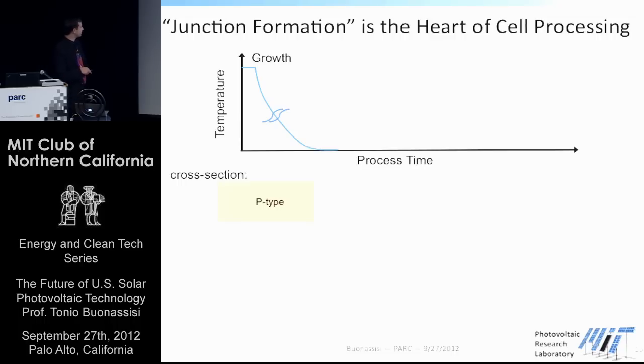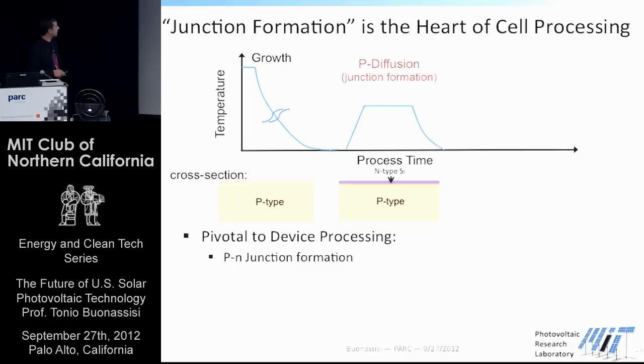This is the cross section of the wafer right here, and it happens to be a P-type wafer. As we continue with our solar cell processing, we first form the junction, the PN junction inside of the device by diffusing in phosphorus. And for the non-initiated here in the group, what this means is we're creating a built-in field that can separate charge. If we just had this bare wafer, light came in and excited an electron hole pair, they would dance around in a random walk. There would be no potential, no voltage, no buildup of charge. Whereas now we have this built-in electrical field, you can separate the charge that's generated by the sunlight. Very critical step, this junction formation step.